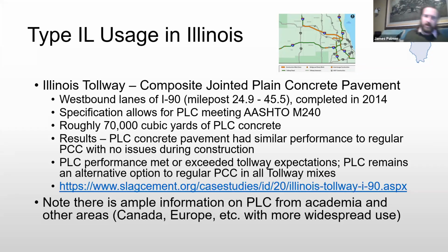So Illinois has had type 1L approved in the DOT spec for some time. I believe it was right around 2012 or shortly thereafter that it went into the spec, but the PLC has not been in the market as an available option. That said, in 2014, the tollway did some composite joint plain concrete pavement and completed that project with Portland limestone cement. Roughly 70,000 cubic yards, and the PLC pavement basically performs very similarly to the Type I/II, and they had no issues during the construction, and they've collected some data on that. So that's a project that's been in place for 6 years now that you may not have even been aware of. There is currently a drive to get PLC used in Illinois.